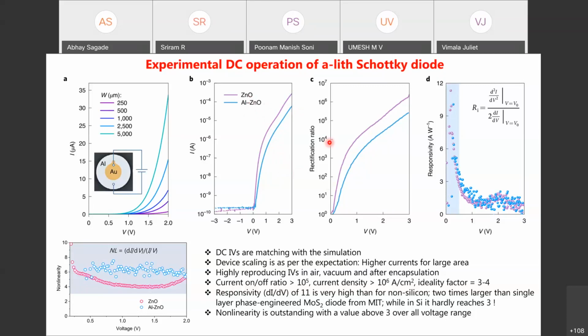The next parameter plotted here is the rectification ratio, and this is the one which decides up to how much frequency you will be able to get good DC voltage, and this has to be as large as possible. This is typically in the range of above 10⁵. This is the ratio of on current divided by off current.